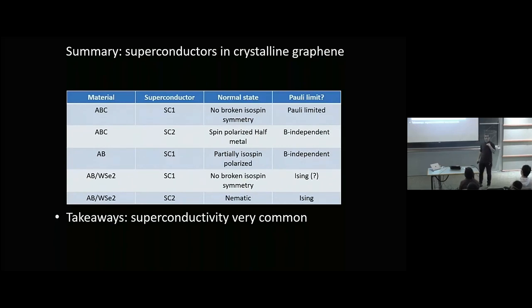I'm sort of skeptical of the idea that it's a particular isospin fluctuation that's really important for a particular order. I think it's more likely that it's either phonons, which I think is quite likely, or something like Kohn-Luttinger. One of the only things that's actually generic to pretty much every single superconductor here, besides the fact that it's in a system that does have phonons, is the fact that there's always a large Fermi surface and a small Fermi surface, and that the large and small Fermi surface is always a similar range of ratios, few to 1, 5 to 1, something like that in terms of area.